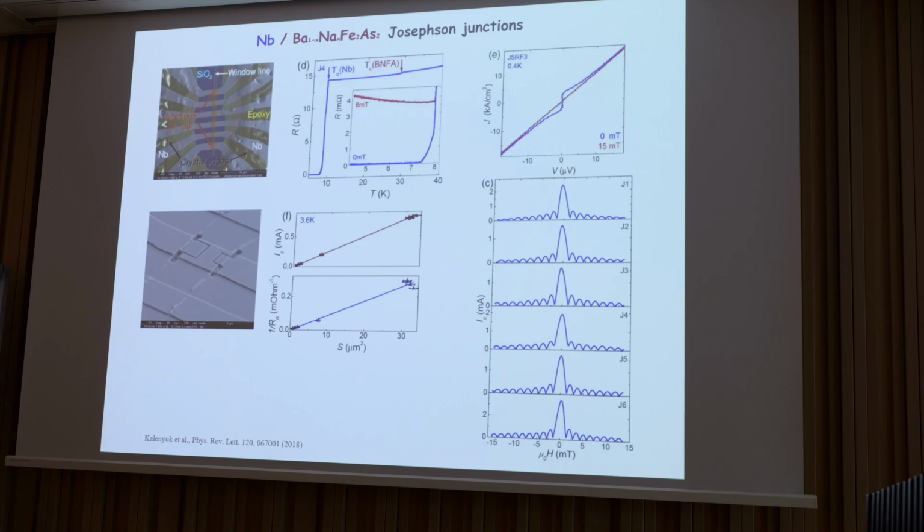Can I add one point? So the cusp is just from the flux flow, right? This is just from surface superconductivity. It appears when the field is exactly parallel. It is flux flow. If you have a component of field perpendicular, then you have vortices, and that gives you resistance. But in fact there is no bulk superconductivity already at this point. It's only surface level. We can talk about it.